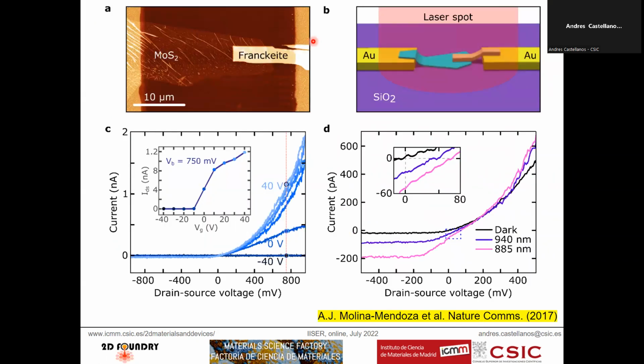So we have a stable P-type narrow bandgap semiconducting material. This is an excellent alternative to black phosphorus if we want to fabricate, for example, heterostructures between N-type and P-type materials. So now we can take a single layer of molybdenum disulfide, which is an N-type semiconducting material. We can transfer it, and we can transfer a Franckeite flake on top. So now we have basically a PN junction right at the junction. And indeed, this device has a rectifying behavior, and the rectification ratio can be controlled with the gate voltage. And as Franckeite can absorb light in the infrared, this has a photovoltaic effect even in the infrared.